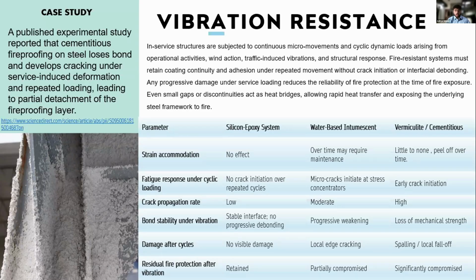Here we observed that in strain accommodation, silicone epoxy had no effect over time. Water-based over time may require maintenance, and with vermiculite, peel off over time will happen. And for fatigue response under cyclic loading, that means multiple loads are being applied. Silicone epoxy has no crack initiated over the repeated cycles. In water-based, micro cracks were seen, and vermiculite started cracking in the early stages.